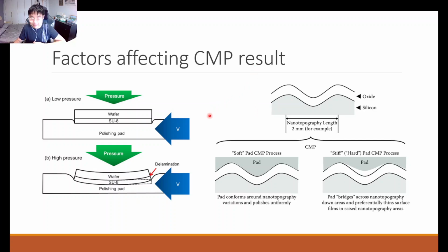And so, as mentioned earlier, things like wafer pressure can affect the CMP result. For example, if you apply too high of a pressure, your pad and your wafer can be, in a sense, slightly distorted in their geometry, and it can also result in a delamination between your wafer surface and the surface of the layer that's laid on your wafer that you're trying to polish.